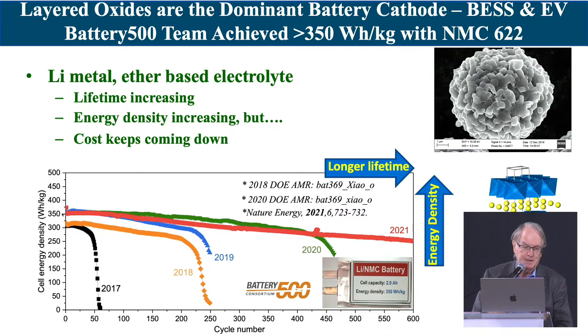And I think you can see in 2017, we had 50 cycles at 300 watt-hours per kilogram compared with the commercial of about 250. A year later, we're up to 250. The following year, we increased now the energy density to 350. And as of this summer, we've got about 800 cycles at 350. So we're showing you can do this. And these cells are using pure lithium metal, and they're now using ether-based electrolytes, not the common carbonate ones that have been used before.